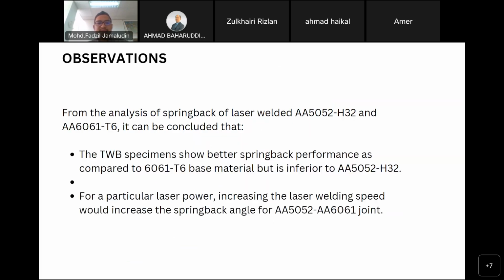So what we have observed is that the spring back for tailor-welded specimen has a better performance as compared to 6061, but it is inferior to 5052. And for particular laser power, increasing the laser welding speed would increase the spring back angle for the joint.